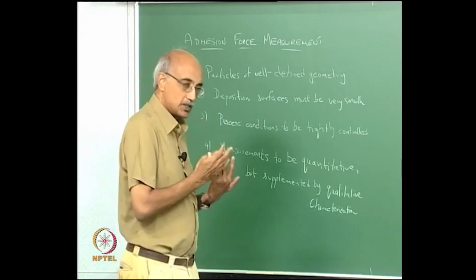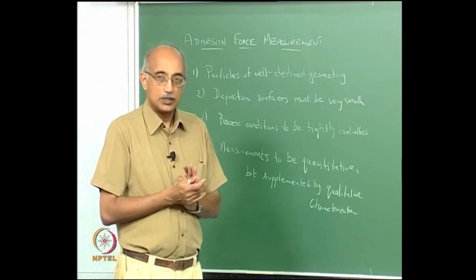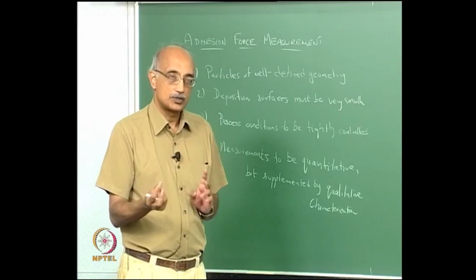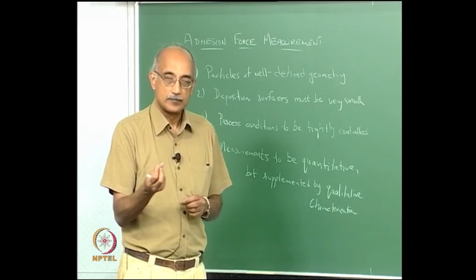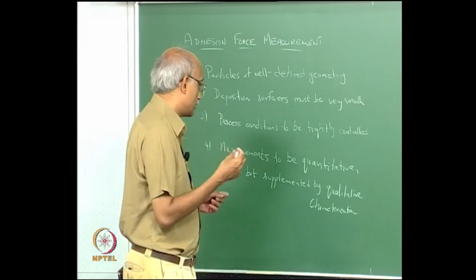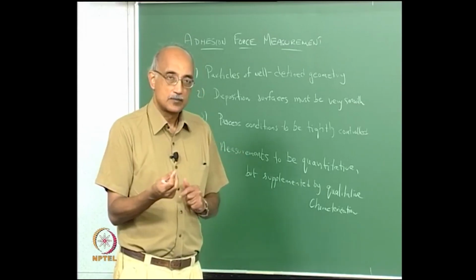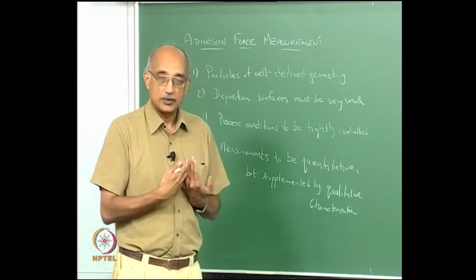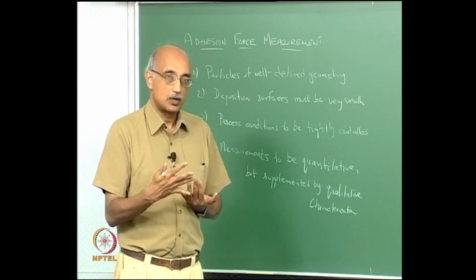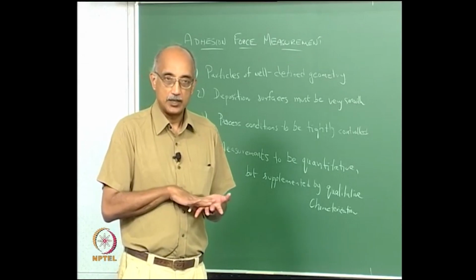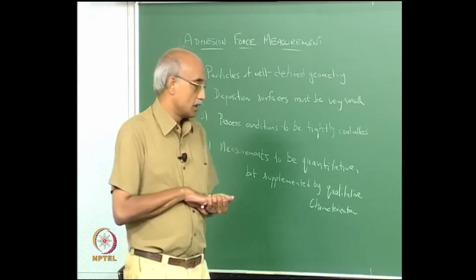Now, that is essentially a quantitative method. What you are really doing is, for every application of force, you are counting the particles before and after, and the removal efficiency of the particles and the corresponding force that has been applied gives you an indicator of what is the adhesion force binding the particle to the surface.